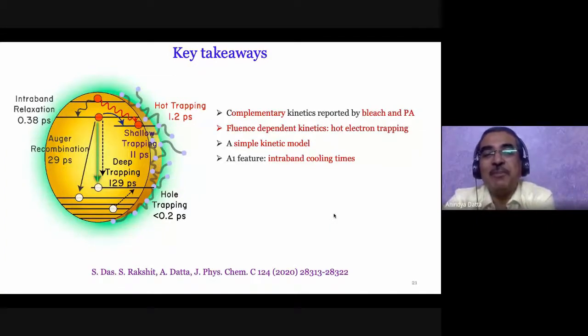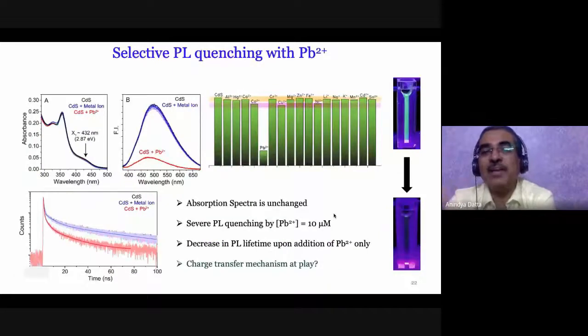And once again, using all our femtosecond spectroscopic methods, we could work out the dynamics of all photoprocesses that take place here. The one proof of concept application that we have seen is that the photoluminescence of these nanoparticles is quenched selectively by lead. No other metal ion that we studied does this, which is good because, as we know, lead is a toxic material. So sensing lead is something that people are worried about. But why is that so?